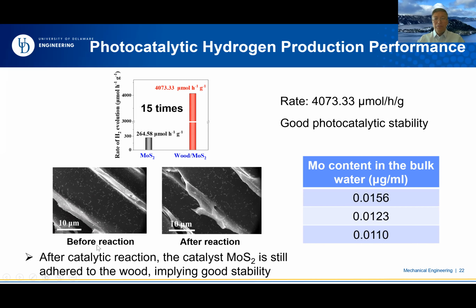And as you can see here, before the reaction and after the reaction, there's no big difference. And then also we test a possibility that molysulfide will detach from wood into water. We test the bulk water after reaction for some time, and we detected a trace amount of moly, indicating that a small amount of moly detached from the wood structure, but not a significant amount.